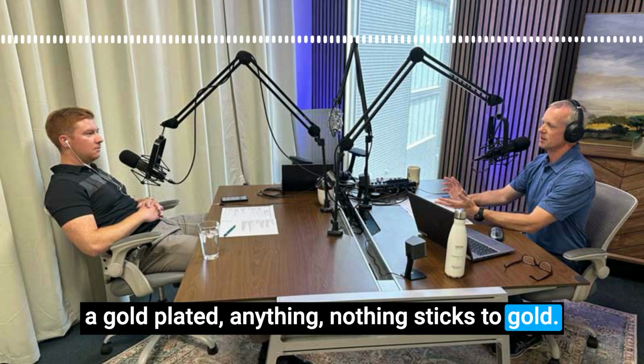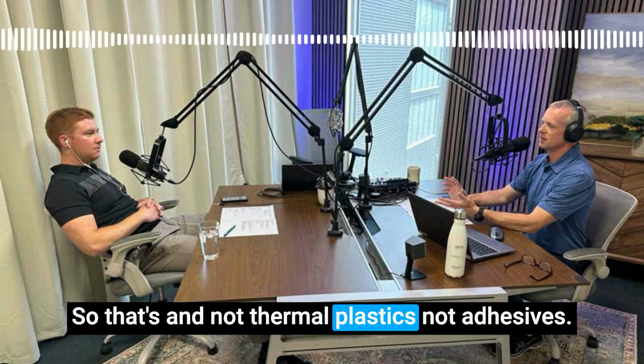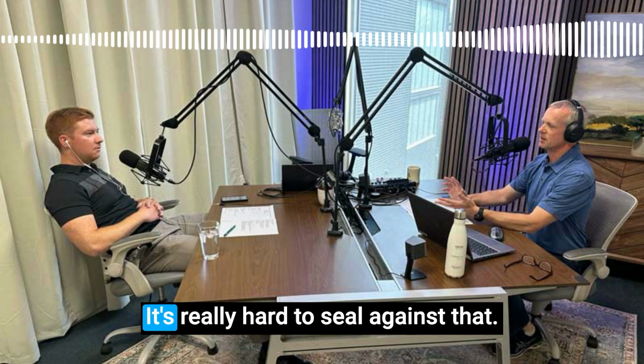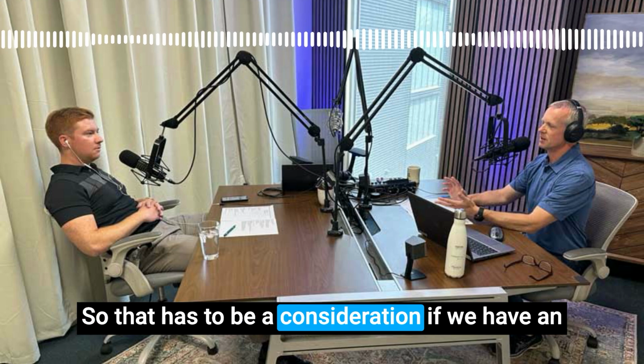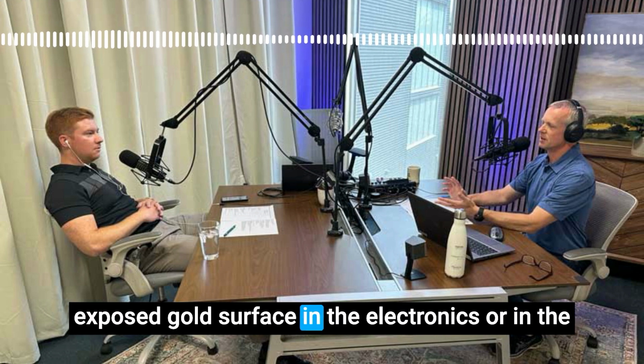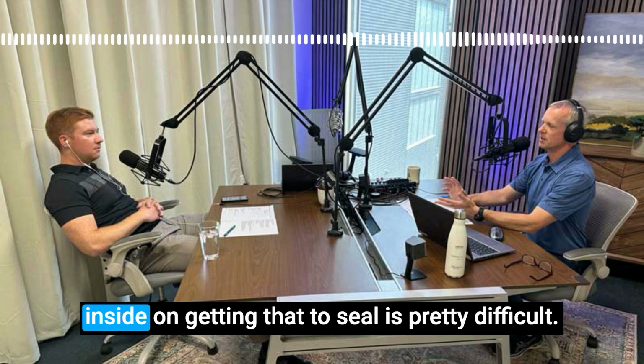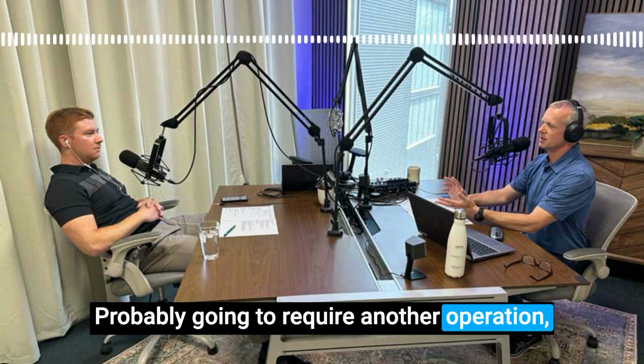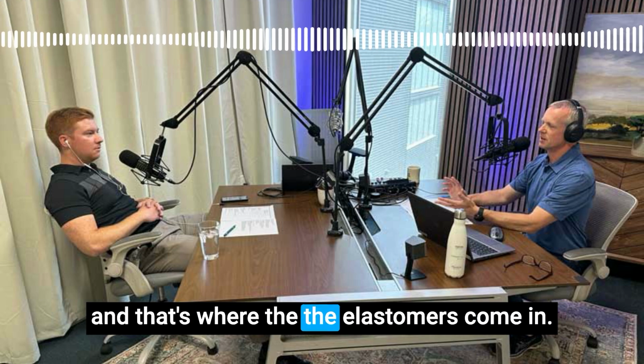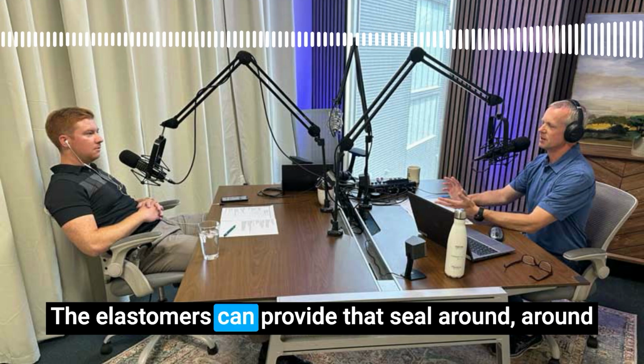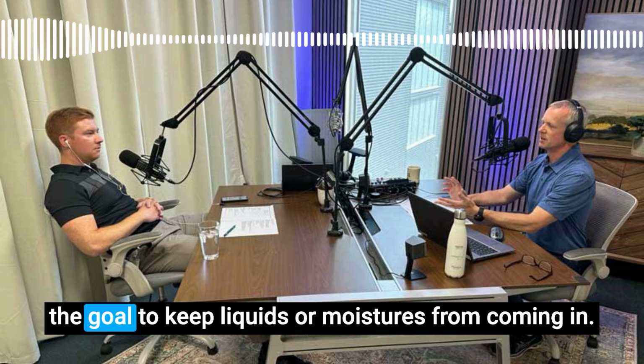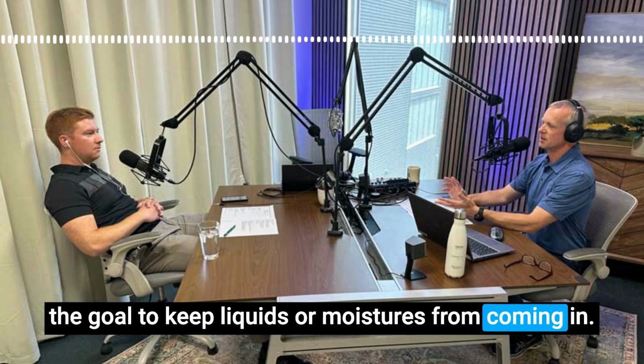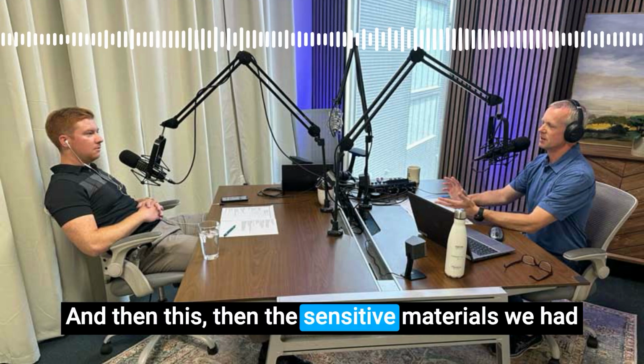Nothing sticks to gold. So not thermoplastics, not adhesives. It's really hard to seal against that. So that has to be a consideration. If we have an exposed gold surface and the electronics are on the inside, getting that to seal is probably going to require another operation. And that's where the elastomers come in. The elastomers can provide that seal around the gold to keep liquids or moisture from coming in. And then the sensitive materials.